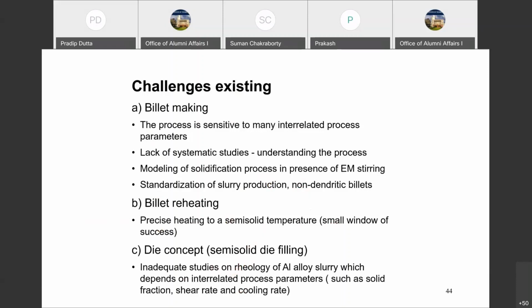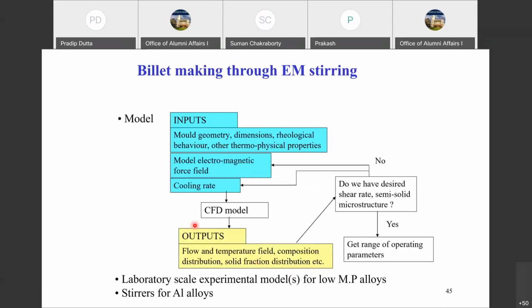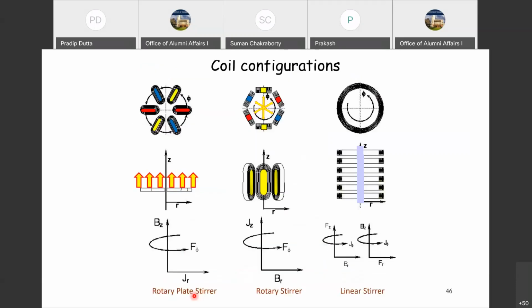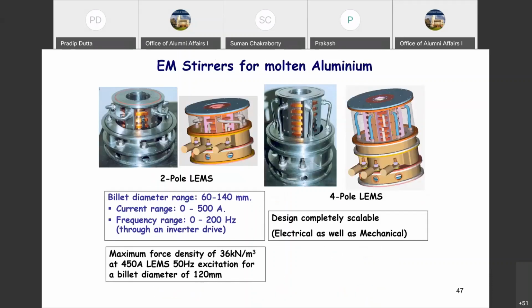Okay. We also needed to study the rheological behavior of the aluminum alloy at the elevated temperature. So that is another separate study which I am not elaborating now. Of course, we start with the model, then we did lab scale experiments for low melting point alloys, and we built our own stirrers for aluminum alloys. There are different types of stirrers. Of course, these are rotary plate stirrers, and this is the rotary stirrer, and then this is actually the linear electromagnetic stirrer. And this particular stirrer is what we designed and built for aluminum melting and stirring, aluminum stirring, in fact. So these are just some of the pictures of the various stirrers that we designed.